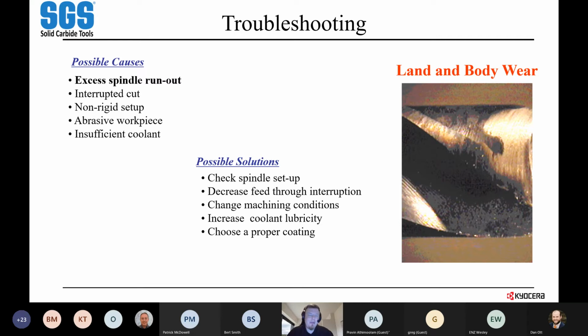So check your spindle setup, decrease your feed if you're in interrupted cuts. Take a look at your coolant situation and see if there's any improvements that can be made there. Don't run crappy castings if you have the option, that is, and then check your coatings. If there is a better coating, or if the coating just is wearing off and it's causing the tool to fail early, then that's something to look at too.